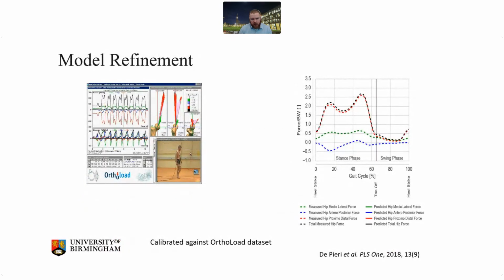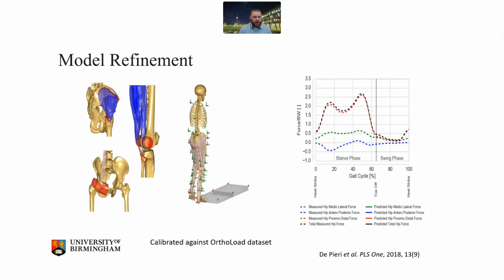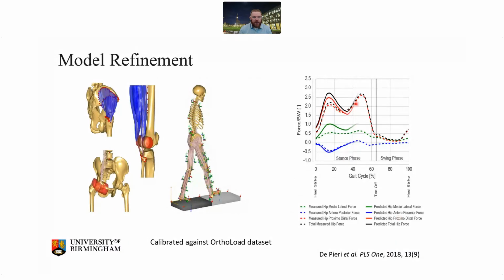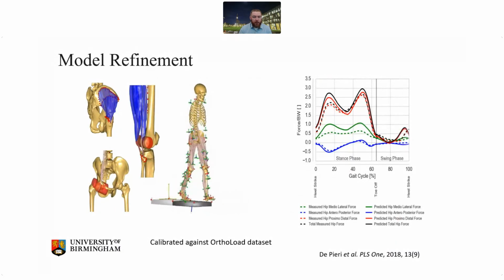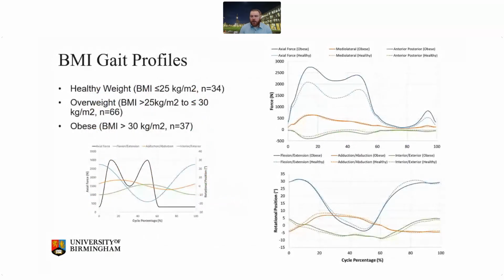The model went through a bit of a refinement phase just to ensure that we were getting something accurate. So we calibrated that model against the Bergmann OrthoLoad data set. What we found was it was particularly sensitive to things like muscle attachment points and the setup. But we came to find a fairly close agreement for the Bergmann inputs to get the Bergmann outputs. And one of the first things we looked at was BMI.